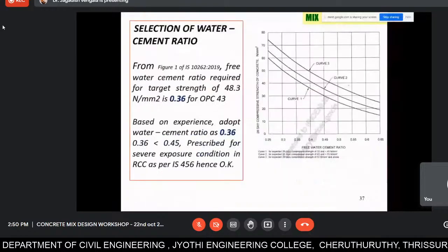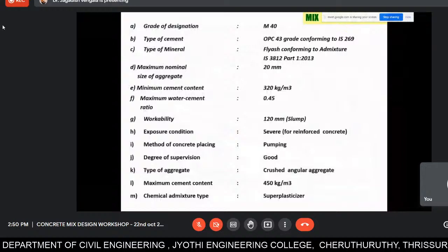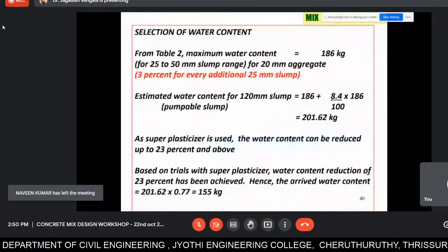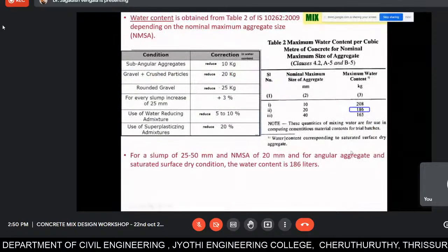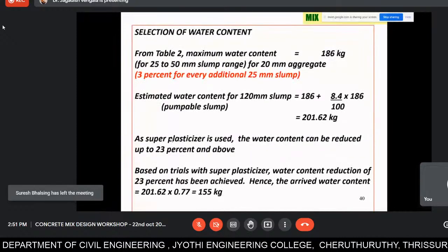But in our case, the data if you see, sorry, I'm going back. In our case, the slump we have to take is 120 mm. So for 120 mm slump, you can see the corrections that are given here. For every slump increase of 25 mm, you have to add 3% correction in water. So 186 liters is your water. Suppose ours is 125 mm. So up to 50, 186. 75, 3%. 100, 6%. 125, 9%. So 9% of additional water correction we have to take.